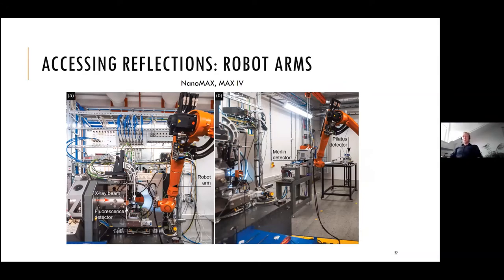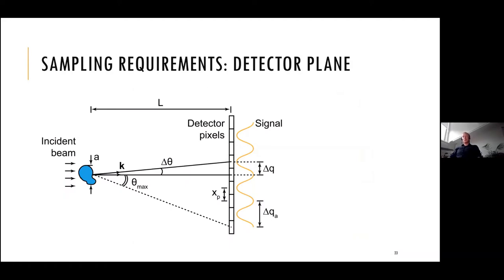What are the requirements for successful measurements? Most important, of course, is the sampling, which was already discussed also in the forward direction. I'm just briefly recapping this. You record your signal by a pixelated detector. So you sample your continuous signal with the pixels, and we can successfully reconstruct something with the phase retrieval algorithms. You need to have this pixel spacing smaller than the inverse size of your object. So you should get at least 3 points per fringe period, let's say, to reconstruct uniquely the signal coming from the sample scattering. Of course, you would like to have much more to get a really nice reconstruction. And this is called the oversampling criterion, and normally it should be more than 2 along each direction in your data.